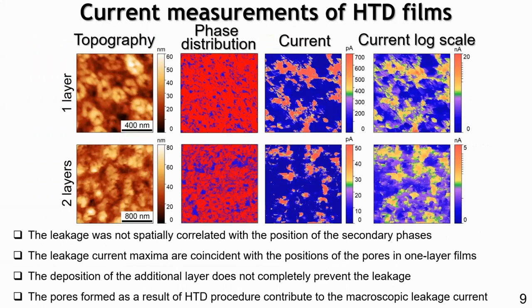When we go to the leakage current measurements, this is the same region in which we studied the phase distribution by the described techniques, and in exactly this position we also measured the current. This is the current on the normal scale, and this is the current on the logarithmic z scale, and you may see an interesting thing. First, we have a real increase of the current in the pores. It's reasonable because we have a smaller resistance in the pores, and they can conduct much more.